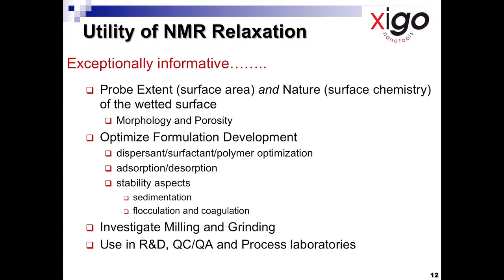NMR is also very useful in optimizing formulation development, because the liquid binds to the surface, and anything you put in the liquid — such as a dispersant, surfactant, or polymer — will affect the relaxation. It affects the relaxation of both the bulk liquid and the bound liquid. Because if anything adsorbs on the surface, it must displace the bound liquid, thereby changing the relaxation, so we can study adsorption and desorption effects.